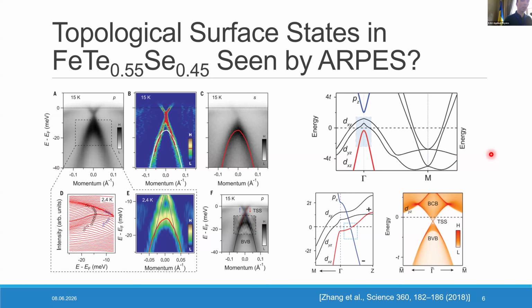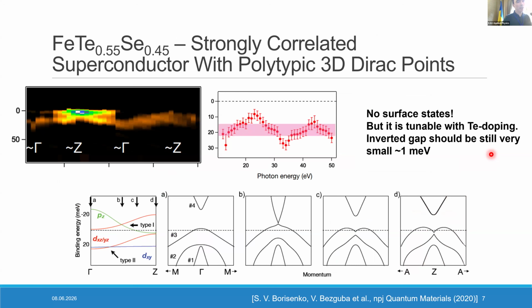In calculations the inverted gap was expected to be around 5 meV, but of course iron-based superconductors are strongly correlated, and you need to take into account the renormalization. After renormalization and after carefully comparing synchrotron measurements to the theory, we found out that the size of this gap can't be larger than 1 meV, and in general our interpretation of the results was that this is a superconductor with trivial electronic structure. There are no surface states.